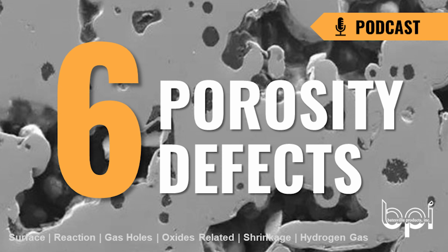As I said, the hydrogen is throughout the melt. So it's going to be everywhere in the casting. It's not going to be localized. So it's very easy to tell if you have a hydrogen porosity issue. It's not going to be on a surface. Your surface is going to look fine. But if you machine the part, you're going to see the holes. If you cut the part and section it as it's shown here, you're going to see the holes throughout.